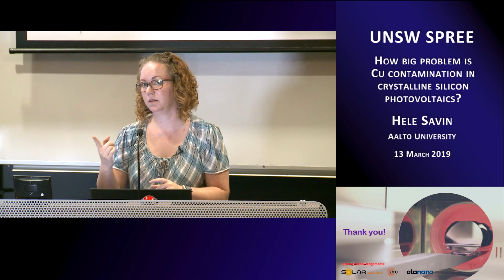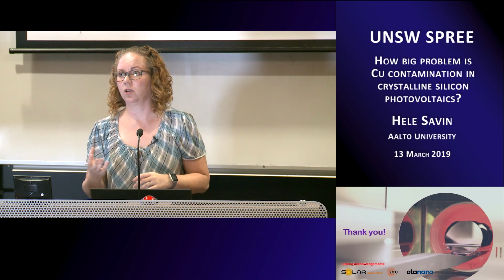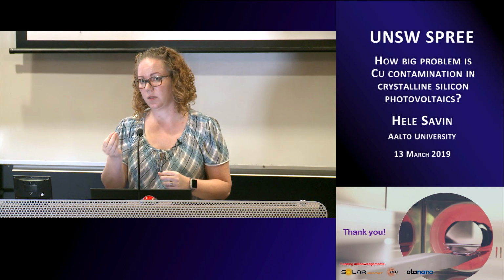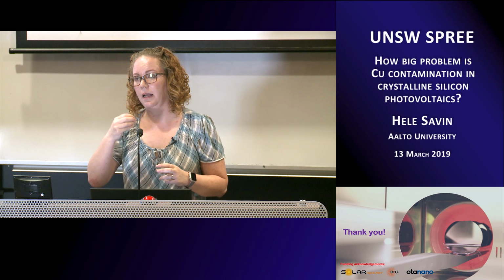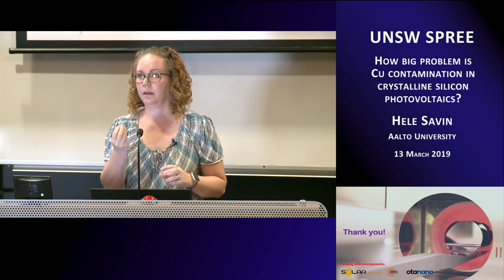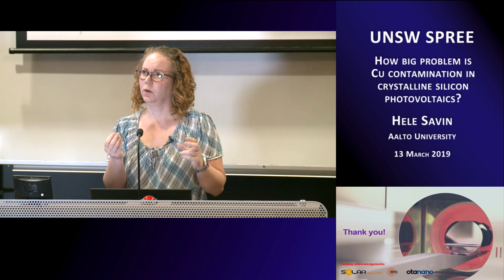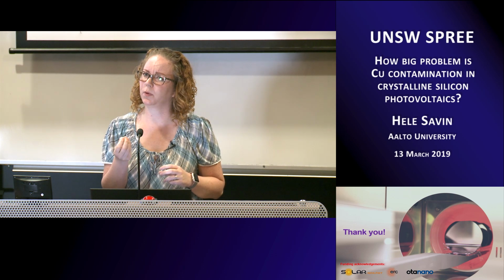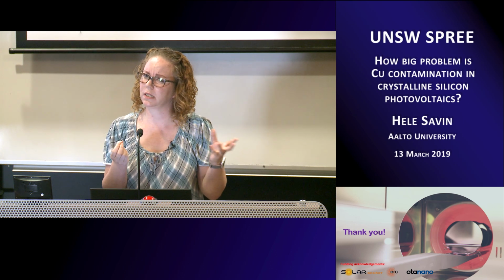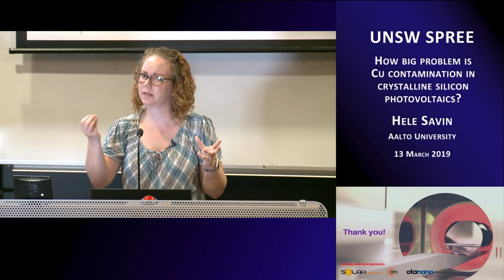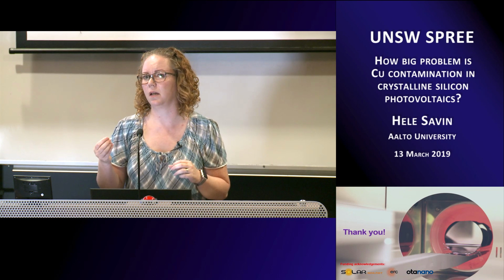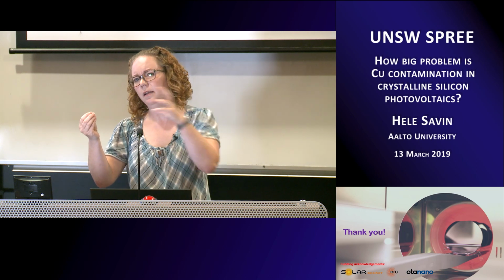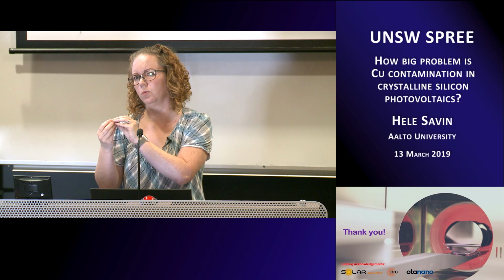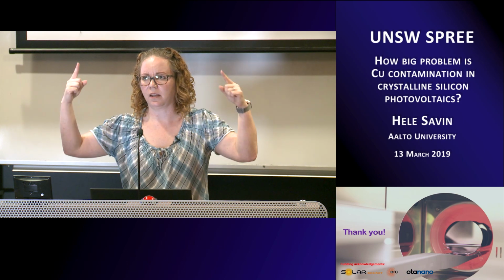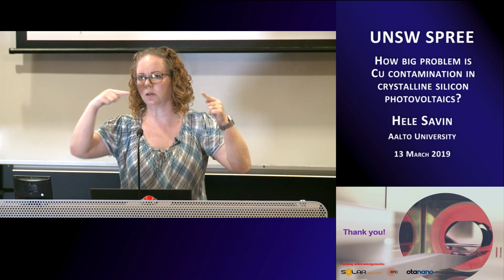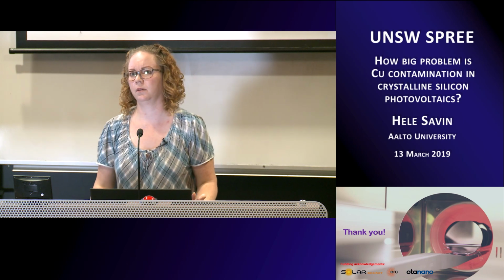And the oxygen question is that it is not really interstitial oxygen, but when we have small oxygen precipitates, they are sort of nuclei for these copper precipitates. Copper can precipitate homogeneously, so it doesn't have to have nuclei, but it would be similar to, let's say, in multi, where you have some dislocations or defects, so the nucleation barrier for copper is much smaller at those places than in perfect silicon, where just two copper atoms have to come together. So if there is a dislocation or something, they will rather go there.